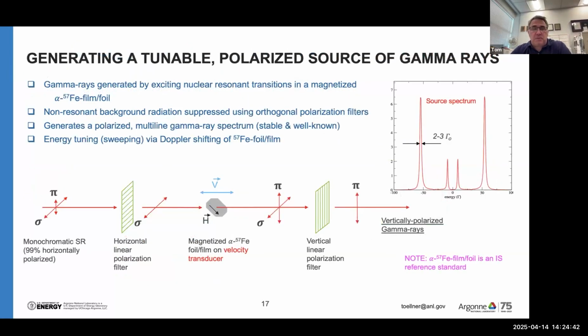So to generate this gamma ray source, we're going to use some polarization filters. If you start from the left, the synchrotron radiation is already highly polarized, but it still needs to be cleaned up because we cannot have any contamination at all. At least we would need to reduce that to well below the nuclear resonance signal. So what we do is we introduce a horizontal linear polarization filter. This purifies the polarization to probably a part in 10 to the 11 or so. Actually, no, a part in 10 to the 9, sorry.